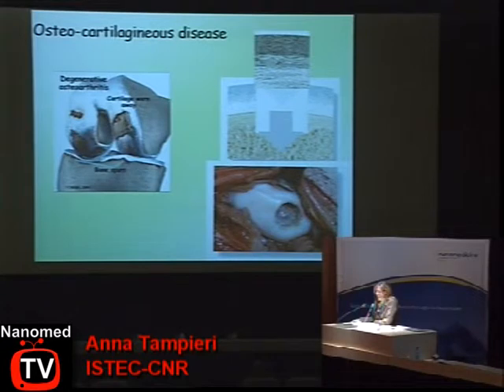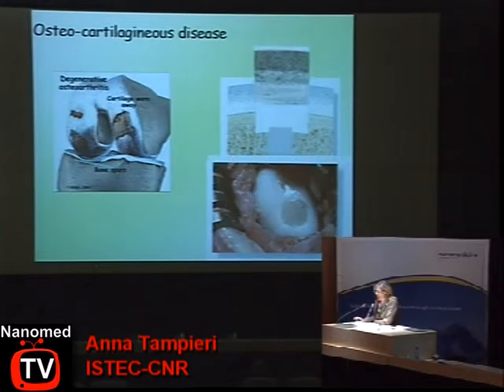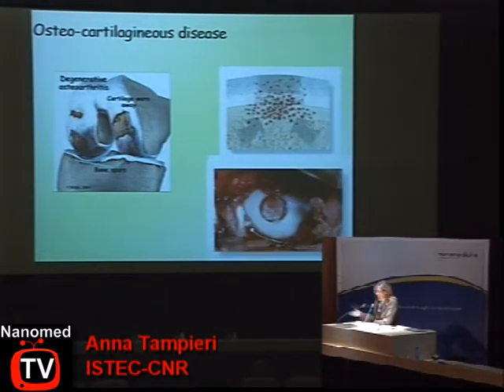So our aim was to try to develop a compositionally and morphologically graded scaffold to repair osteochondral focal defects with a small to medium dimension. And the pushing idea was to produce a scaffold able to mimic the complex composition of the osteochondral region, to be inserted in the defects, exploiting the blood from the subchondral bone to have the differentiation of mesenchymal cells passing through the scaffold and in contact with different signals from the scaffold, to induce differentiation in osteoblastic cells in the bony layer and chondrocytes in the upper layer.